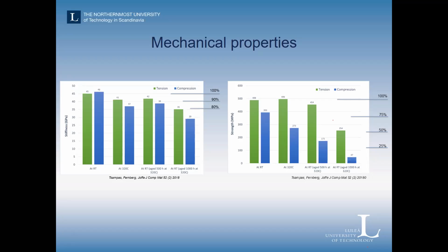If we increase the temperature to 320 degrees and test the properties at that temperature, there is a decrease mainly in compressive properties in terms of stiffness. And if we go further to the right in the stiffness graph, we find specimens that are tested at room temperature but were aged, in one case for 500 hours and in the other for 1,000 hours at 320 degrees. When we compare to the first graph, there is of course a decrease because of the aging, and compressive properties decrease more than the tensile properties. The difference is very much magnified if we look at the strength properties to the right.